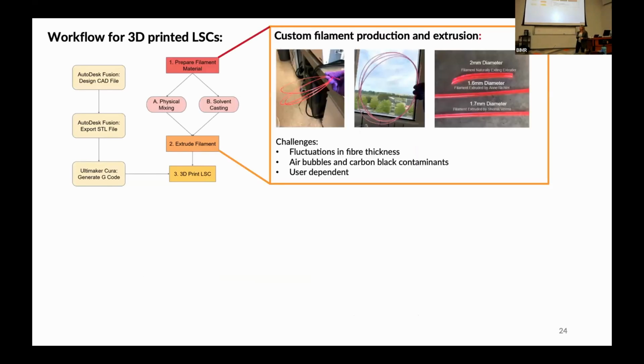Making fiber, extruding fiber that is within the tolerance limits of your 3D printer is not easy when you haven't done it before. And it's really student dependent. So you've got filaments here prepared by different students and also just let to extrude naturally. Doesn't look like there's a big difference, 2 millimeters to 1.7 millimeters. A 2 millimeter diameter will fail in the print. And the problem is it's not just at one point, so you might be printing for 5 hours and suddenly your fiber is just outside the tolerance limits and your print just fails. This is one of the challenges.